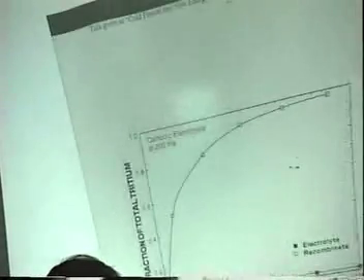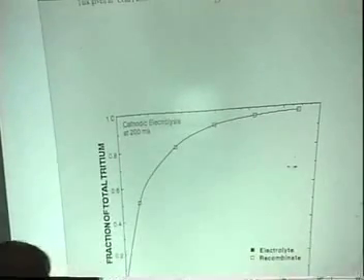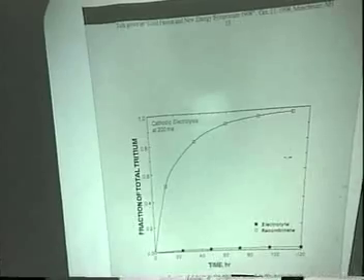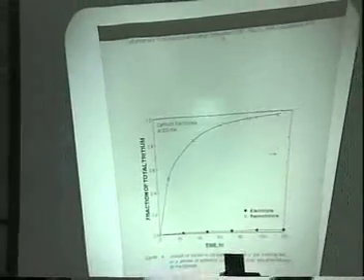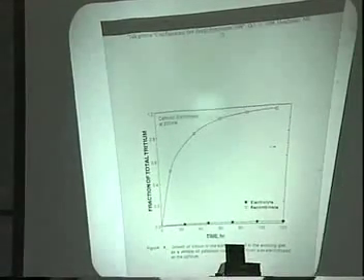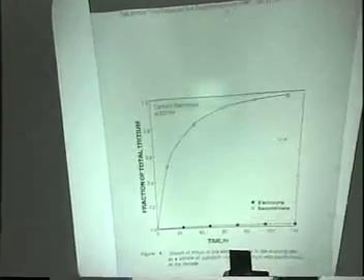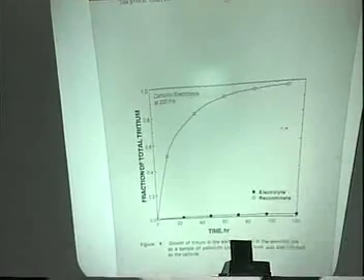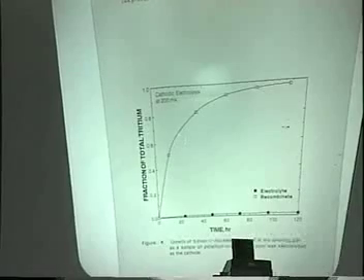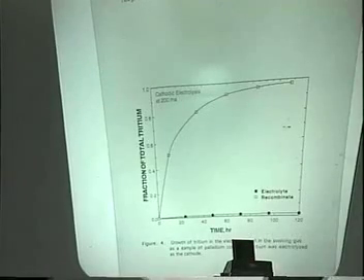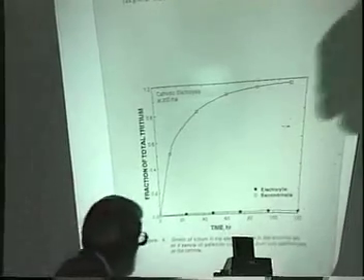We were also able to show, using the tritium as a tracer, how this loss here is a first order reaction. We could relate that to some of the properties of the palladium, and we could understand why it is that the tritium was going into the gas phase. Well, all that was very interesting, but again, it had essentially no effect on the skeptics.